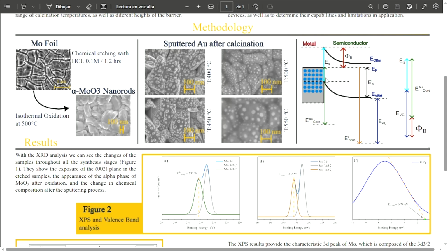When a semiconductor is in contact with a metal, their Fermi levels are different. So there is a bending of the semiconductor band near the interface. But despite this bending, parameters such as the band gap, for example, do not change. However, there are others that do, such as the energy at the core level, which in this case tends to be lower due to the band's bending, or the Schottky barrier, which does not exist in the semiconductor material away from the interface, but at the interface it does exist.